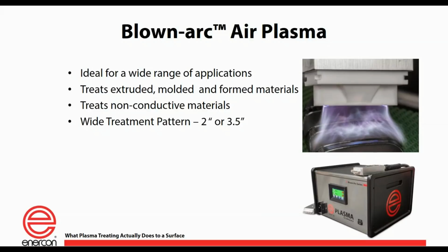Now, we have another that was not shown in that video. We have a blown arc, which is similar to a blown corona. The treatment head is about 2 to 3.5 inches wide, so it's about the area that you're going to get treated. It can only be used on non-conductive parts, so this is mostly for plastics, and it's ideal for a wide range of applications. Generally speaking, we use it for labeling applications and things such as that, or maybe even printing applications when you only have to bump the dyne level of the surface energy up a little bit. You're not going to get quite the intense nature that you would get from a flame or a plasma with the blown arc. But again, if you're starting at 30 or 40 dyne and you only need to go to 45 to 50 dyne to get a good treatment, this may be a good option. And again, it covers a much larger area than just a regular plasma.